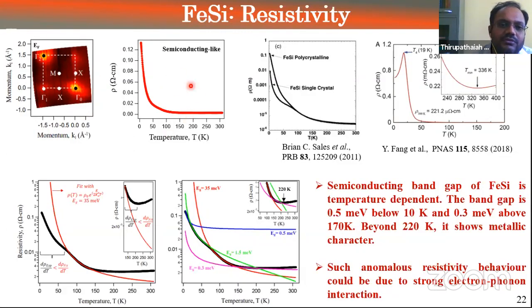So then we thought maybe we were wrong in measuring resistivity, but when we compared with the existing literature, this is okay, not that bad. And recently there was another paper which says that in fact at around 19 Kelvin it becomes a metal, and they suggested that it's because of the topological surface states. Of course, that was another motivation for us to study this. So this says that there is something messy, and we wanted to analyze thoroughly what's happening here.